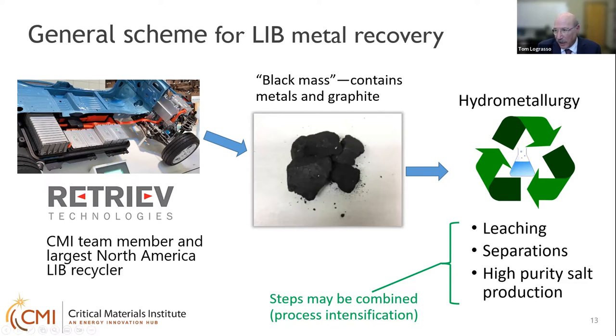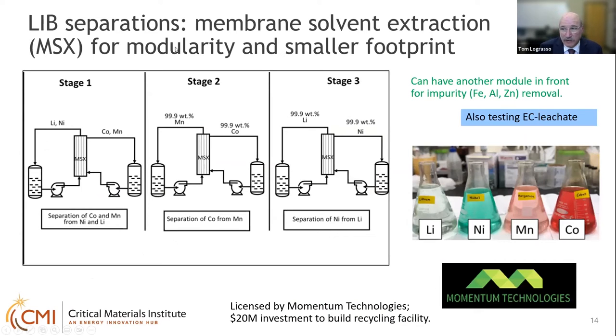And we've been trying to take the hydrometallurgical approach of leaching, separating, and then producing high purity salts. We've been looking at ways to combine these three steps to reduce the energy intensity of the process. One example of this is, again, the membrane solvent extraction. It was developed for rare earths, but it's equally applicable to the black mass. We can develop a three-stage process where we separate the cobalt and the manganese from nickel and lithium in the first stage. The second stage separates cobalt and manganese, and the third stage separates nickel from lithium. So again, we're taking it all the way back to the elements, and we produce four independent liquors of lithium, nickel, manganese, and cobalt.